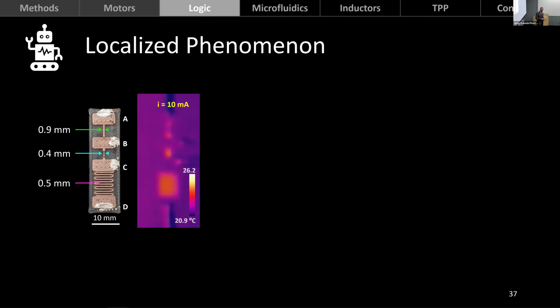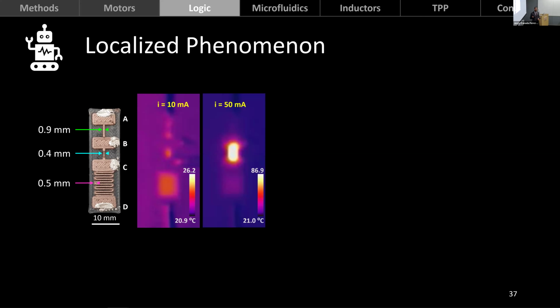And so if we look at thermal images of this sample while applying a low current, we see that not much is happening. But when we apply a higher current, we see that indeed it is that segment, the one that heats up excessively, while the others sort of remain undisturbed.